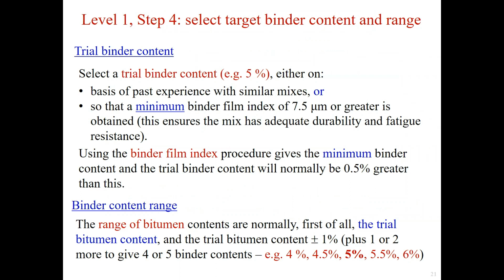The binder film index is a measure of the average binder film on the aggregate particles, excluding any binder which might be absorbed by the aggregate. This allows the mix to have adequate durability and fatigue resistance.